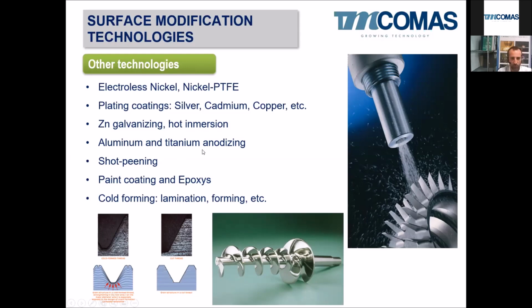On aluminum and titanium parts, we can do anodizing, which is an electrolytic process which creates a hard and thin protective coating on the surface of titanium and aluminum. Shot peening is a very interesting technology to modify the residual stress in the surface. It is based on the impingement of shot particles on the surface, and the surface gets a compressive residual stress that delays the appearance of fatigue stresses. So it's a technology that is very used in aeronautic applications.